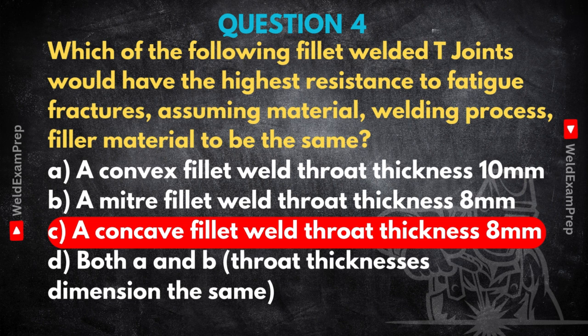Okay. Now think about the weld toe, that little transition point where the weld blends into the base plate. A convex fillet weld, option A, even though it's bigger overall with that 10 millimeter throat, tends to create a sharper angle right at that toe. Right, it bulges out, creating a steeper transition. That sharp corner acts like a little notch, concentrating the stress every time the joint is loaded. It's a prime spot for a fatigue crack to start, even with more weld metal there. Like a weak link in the chain, geometrically speaking?